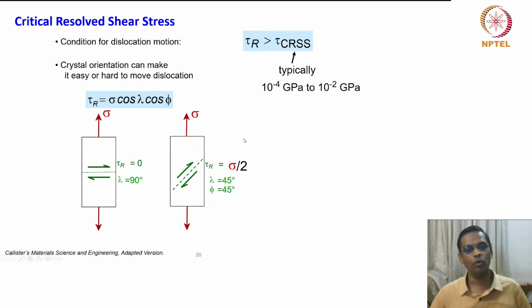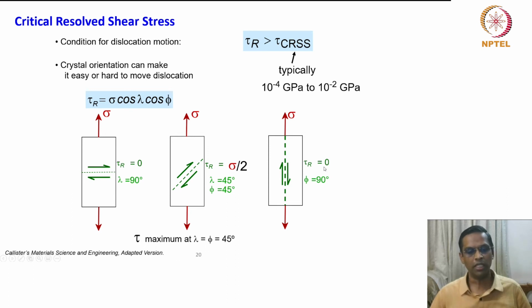On the other hand, if you take lambda and phi as 45 degrees, then it gives a value tau r is equal to sigma by 2. On the other hand, if you make phi equal to 90 degrees, then also tau r becomes 0. So what it means is that tau is maximum at lambda and phi equal to 45 degrees.